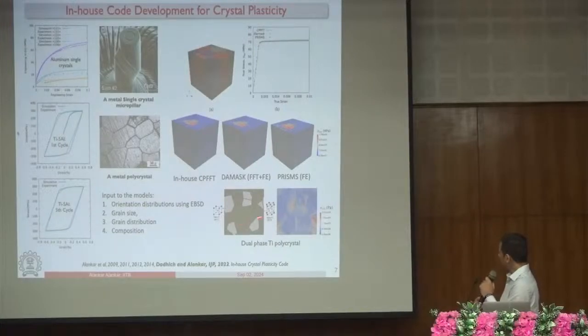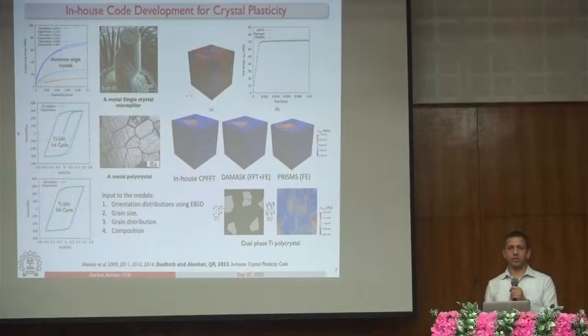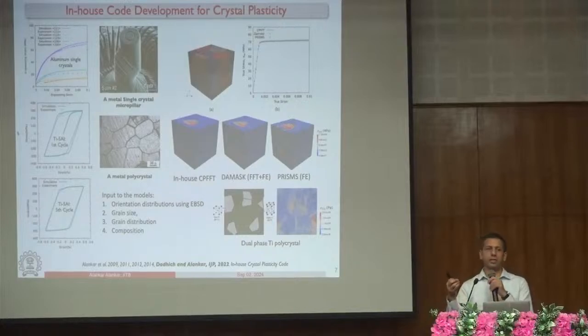Right? Our programs can handle multiple models in a single simulation. I can introduce one type of model in one grain, another type of model in the other grain, and so on. I can run an atomistic simulation for one grain and a continuum simulation in the other grain. This work was published recently, in 2023, in the International Journal of Plasticity. Overall, what you need to simulate such things is orientation. Crystallographic orientation means the plane normal to each grain, the size of the grain, how many grains there are, and the composition. Then apply realistic boundary conditions that you observe in the experiment, and you can analyze it. These are things that you will not see under an optical microscope. Some of the things you will not see even in a scanning electron microscope, because it shows you only the surface.